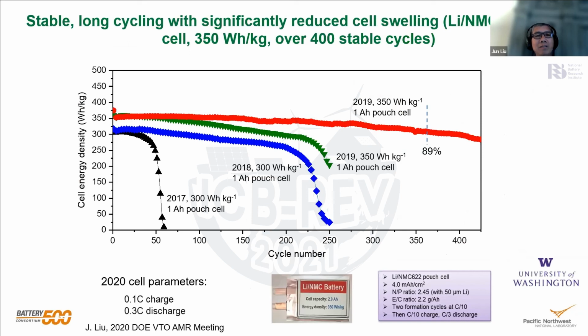It has taken lots of effort in the last 4 years from the team members, many students from the universities, postdocs, and staff members from national labs, for us to come to where we are today. We started with high energy pouch cells, more than 300 watt-hour per kg, much higher than what we could do in lithium-ion batteries. At the beginning of the program, just 4 years ago, we could only get 50 cycles. You can see the progress we are making, and this chart is already outdated. For 350 watt-hour per kg cells, we can already have very stable cycling for very close to 400 cycles. That's exactly what we are shooting for.